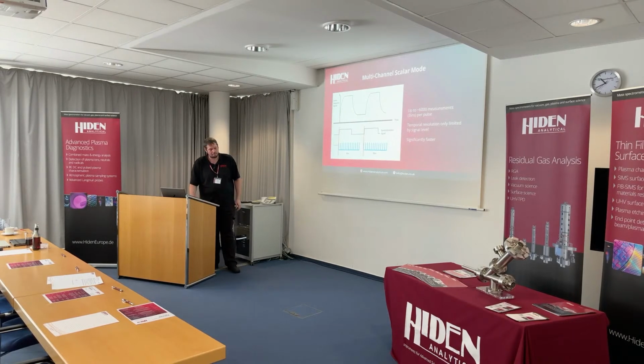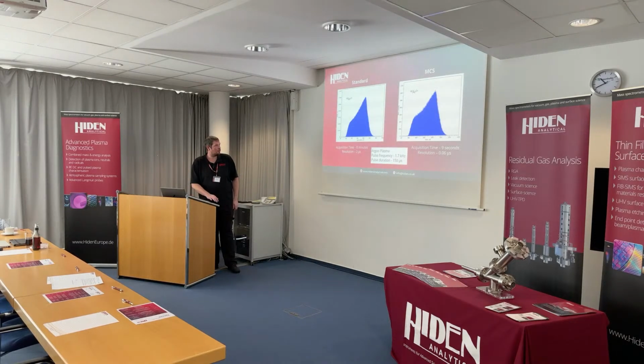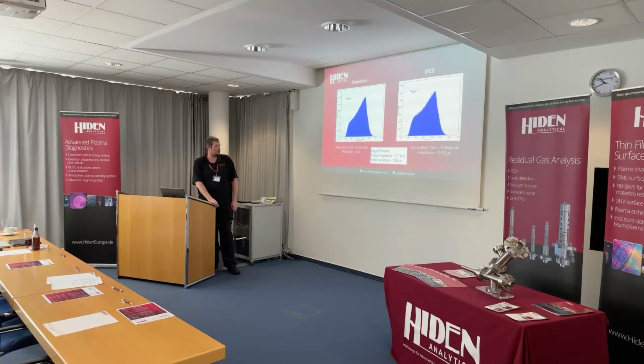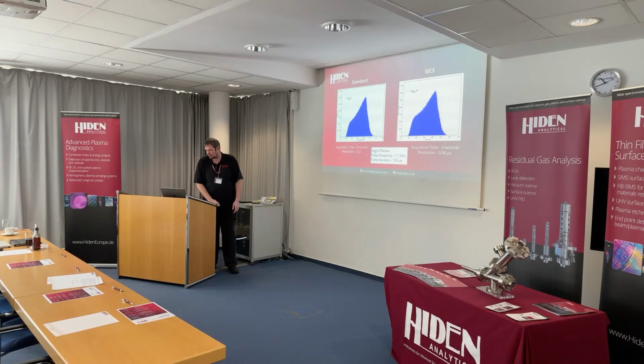So what this looks like is a comparison between the two. This was done on that chamber, 1.7 kilohertz pulse frequency, 150 microseconds pulse duration. You can see the data's roughly the same, but it's the acquisition time: 8 minutes versus 9 seconds. And that's at quite a high pulse frequency. If that was, say, 170 hertz, more like a HiPIMS or something, then 80 minutes versus 90 seconds. Suddenly a lot more things become possible.